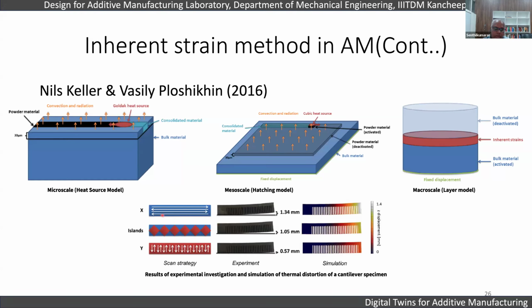So you can see that you have different kinds of hatching strategies you do, and then different levels of deformations you can get. You can see that the scanning pattern has a larger influence on the strains that you can measure. And using the simulation also, you verify the measured values of the deviations against the simulations from the experiments, and then you can just use that to calibrate in the software.